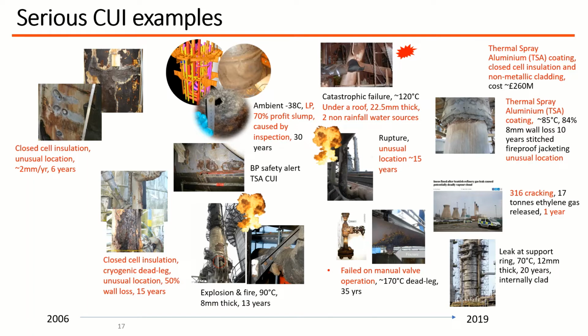So that's why some inspection intervals are very conservative compared with the likely time to failure, or the realistic time to failure. Collectively, they do teach us to be very careful not to make too many assumptions when predicting CUI for highly critical equipment, whether it be associated with wetting, taking credit for different designs, or where the CUI will occur. For quite a few of these, there were no visual signs of CUI before removing the insulation, and many occurred in locations that are considered lesser prone areas, which might not be inspected by some company inspection schemes. So API 581 estimates, however, could well double the CUI timing experience if the plants were located in a landlocked area compared with these marine onshore offshore examples, which I find really interesting.